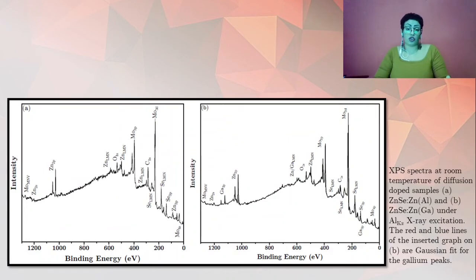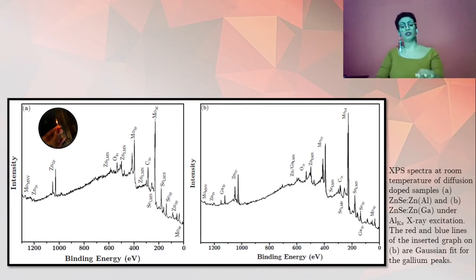X-ray photoelectron spectroscopy measurements were performed to confirm the effectiveness of the diffusion doping process. The spectra of the aluminum-doped sample was acquired after successive sputterings to clean the sample surface, but it was not possible to identify the presence of aluminum in the material. The non-observation of aluminum on the surface of the sample may indicate that the doping process was more effective, since it's probable that the aluminum had penetrated more into the material during the diffusion process than the gallium, concentrating in the bulk of the sample, and the aluminum atoms that remain on the sample surface may have been removed during the sputtering process needed.